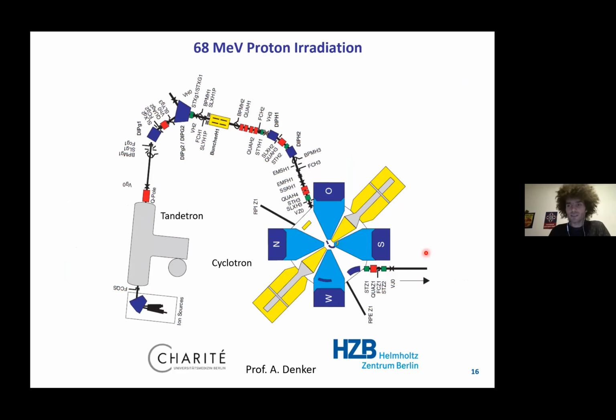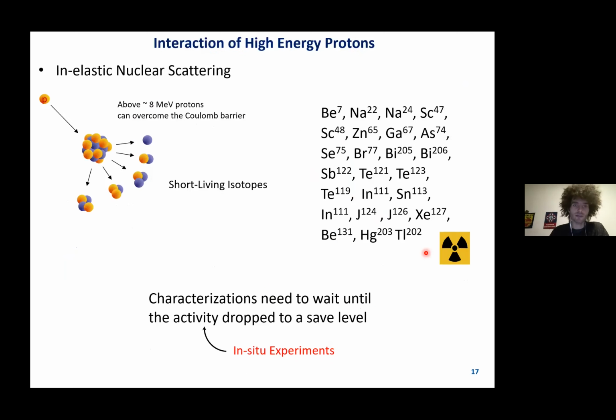The downside of using these high energy protons, while they give you a very homogeneous damage throughout any device, is that you also have a third effect. And the third effect is inelastic nuclear scattering, right? So the high energy protons actually will start to create a bunch of short-living isotopes. And these isotopes here are what I usually find after irradiation of a perovskite sample. Because of this, we usually wait about 2-3 weeks before we start any characterization, just for safety reasons.